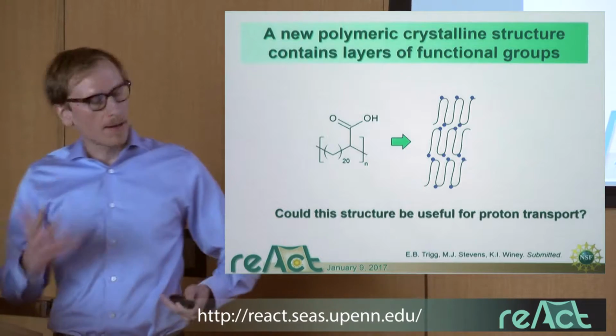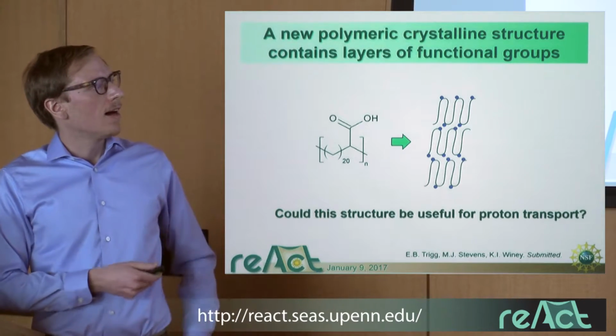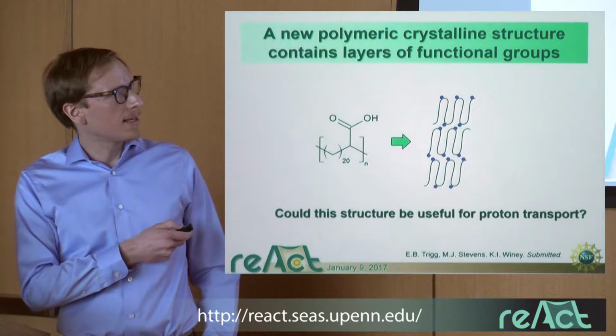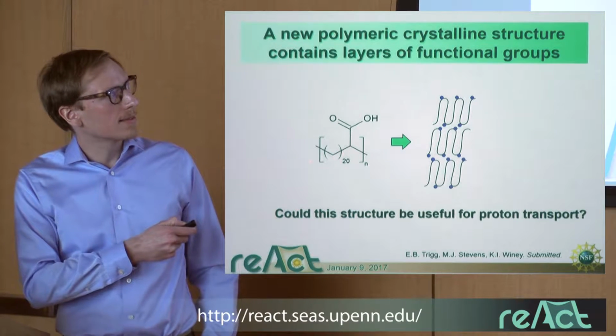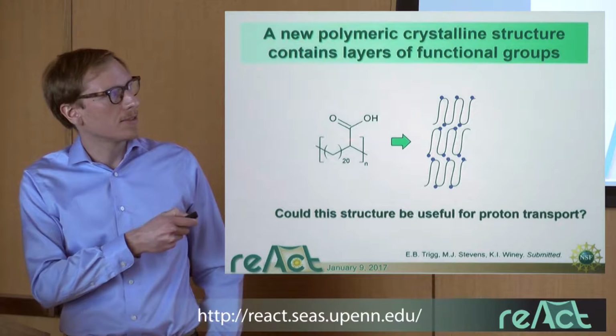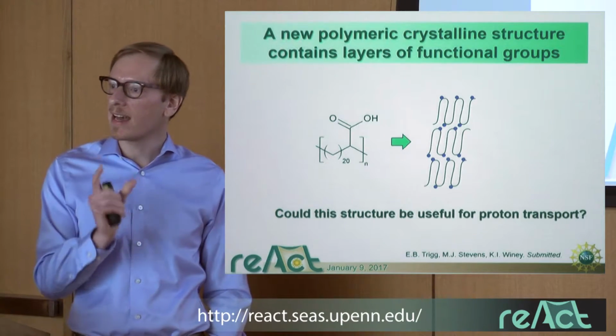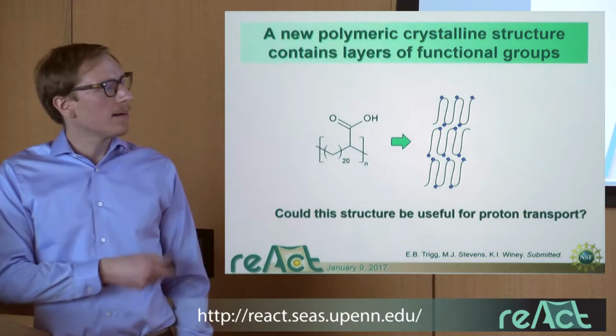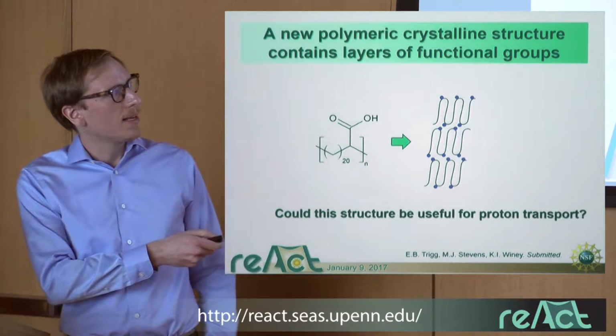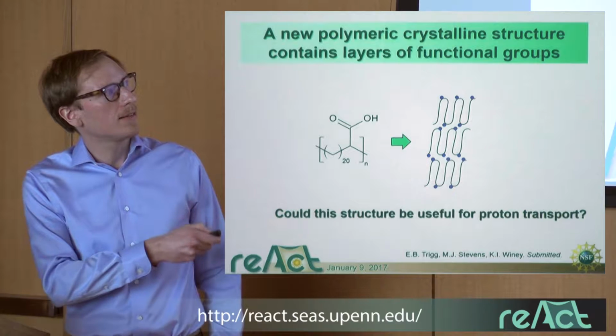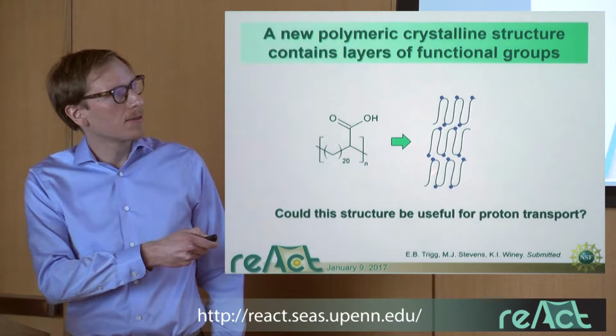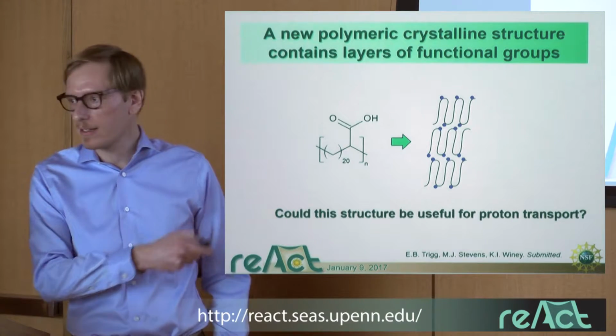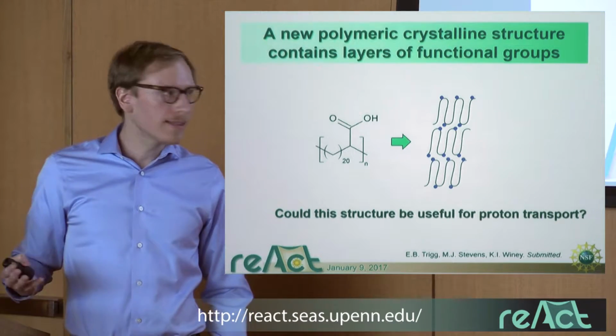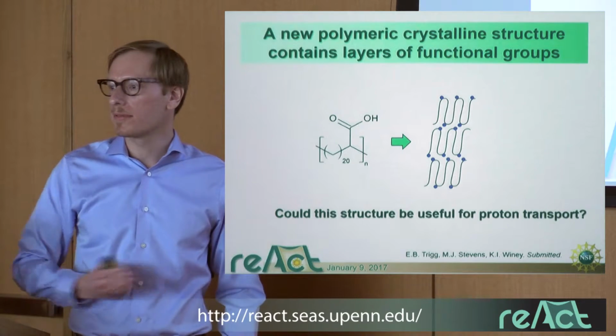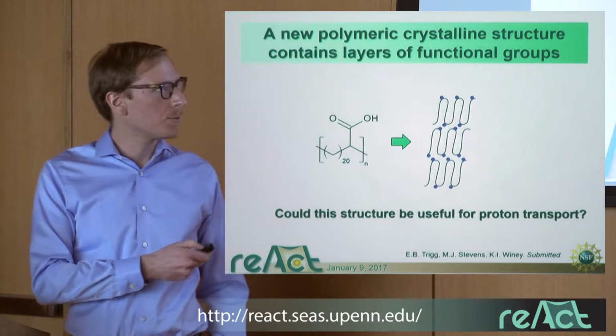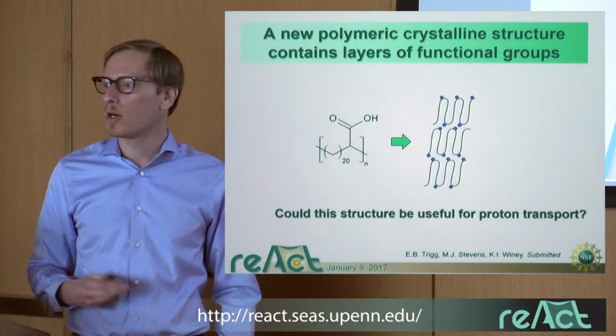Okay, so how did this project come about? I did some work previously studying this polymer here. This is a linear polyethylene with carboxylic acid groups on every 21st carbon, exactly every 21st carbon. And previous work that I did showed that this polymer crystallizes in this way. So the chains are actually folded, forming this multi-layered morphology. So we thought maybe this structure could be useful for proton transport if we replace this functional group with something more appropriate.